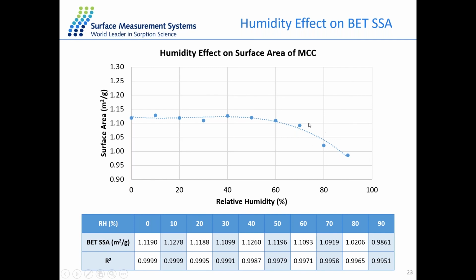However, when the humidity keeps increasing, the measured surface area will decrease, and at 90% RH, the value of the surface area is just around maybe 85% of the initial value at dry condition. And the reduction in the surface area under high humidity environment could be correlated to the granulation or the caking of the cellulose powder.